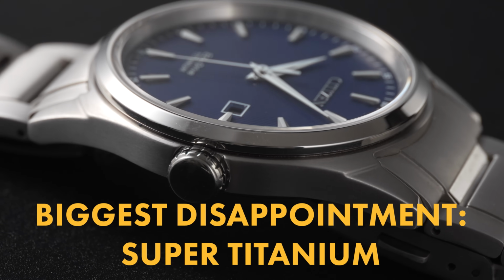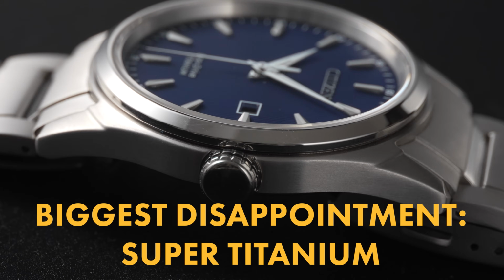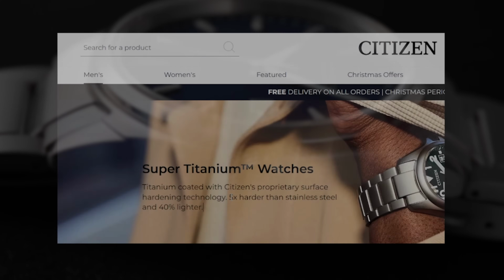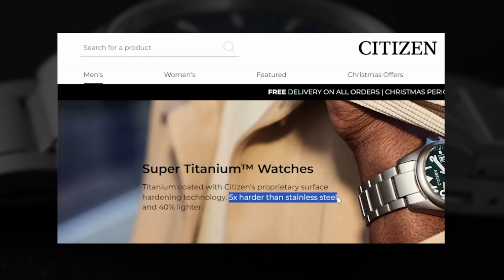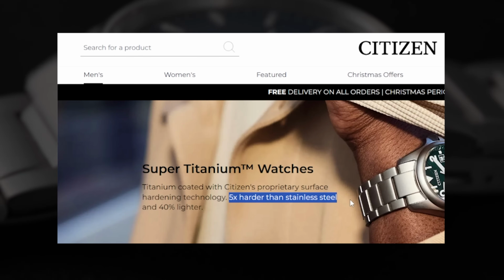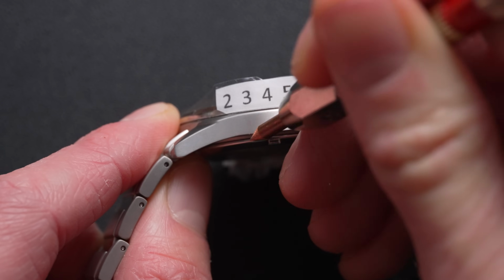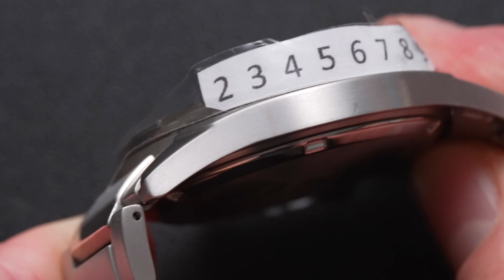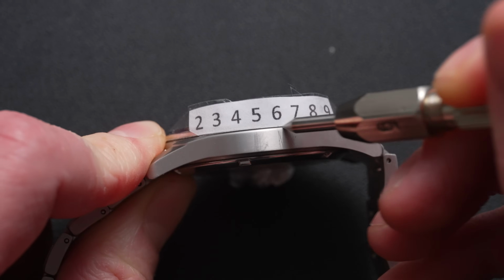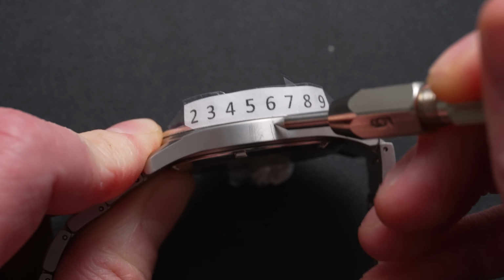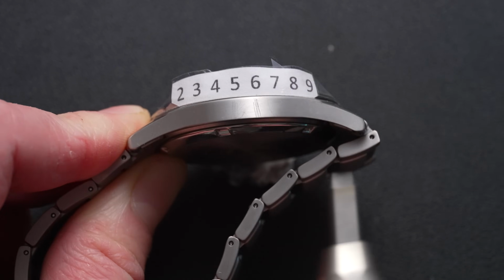The most disappointing award, while there are a couple of contenders, it has to go to Citizen Super Titanium. I expected this to do extremely well, as Super Titanium is advertised as 5 times harder than stainless steel on the Citizen website. Based on my results here though, that's simply not true. It started marking earlier than the steel watches and was eliminated at the same level, with deep scratches at level 6. If anything, it performed marginally worse than the steel watches.